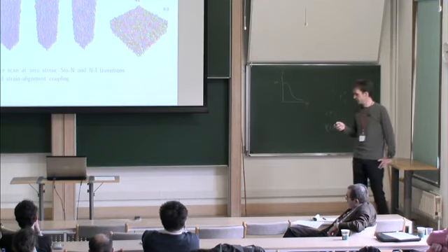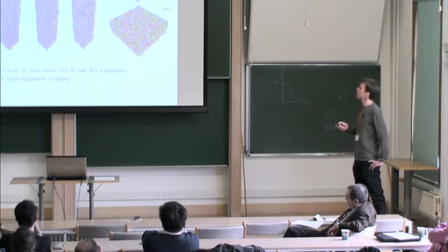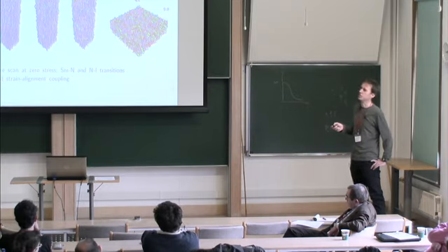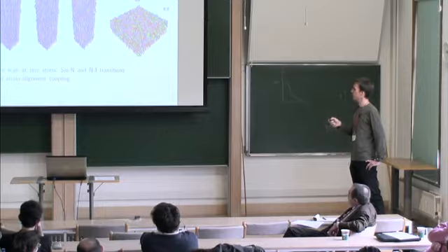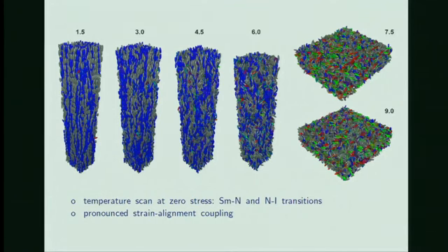Okay, so the first set of results concerns a temperature scan. You recall the sample I was showing you on one of the previous slides. It was blown up by negative pressure shock, right? So what we do first, before starting the simulation, we isotropically compress the sample to almost close packing, and this is what we call then our reference sample. This is the starting point then for all of our simulations.